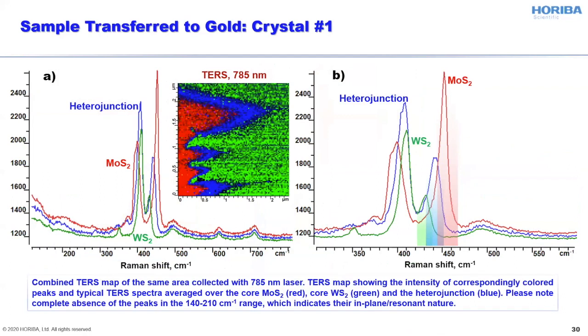Then we took the TERS map image of the same area, the same crystal, but now we switched from a resonant red laser, the 638 laser, to an infrared 785 laser. And with the 785 laser, we are below the band gap for both molybdenum disulfide and tungsten disulfide.